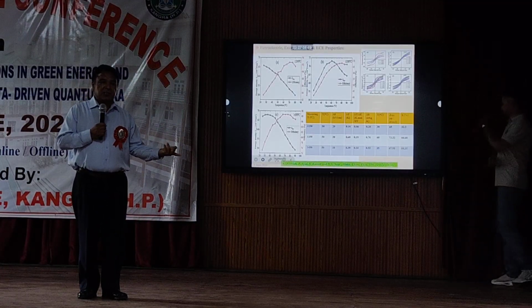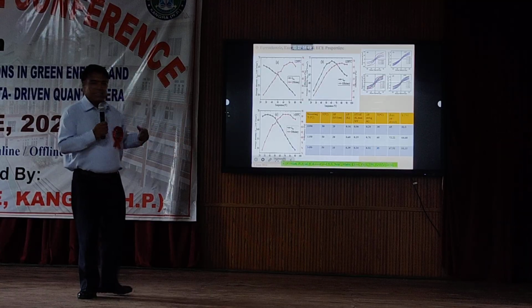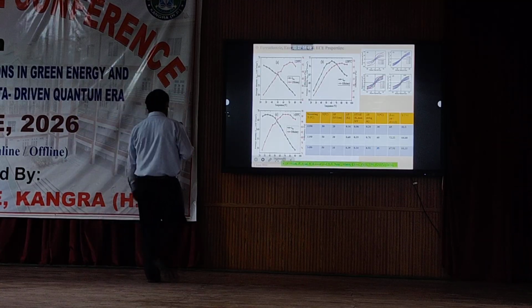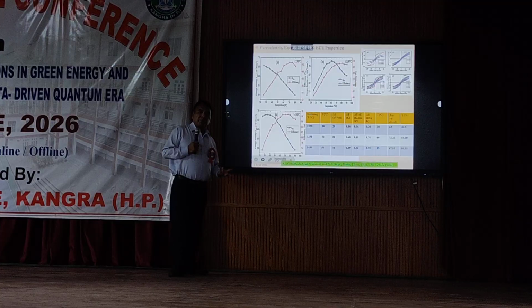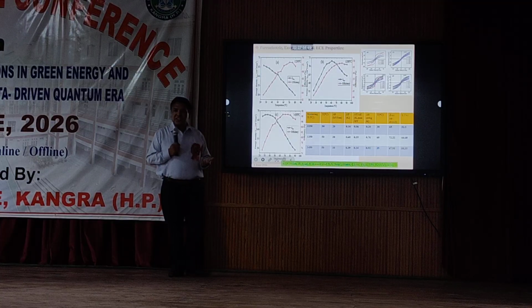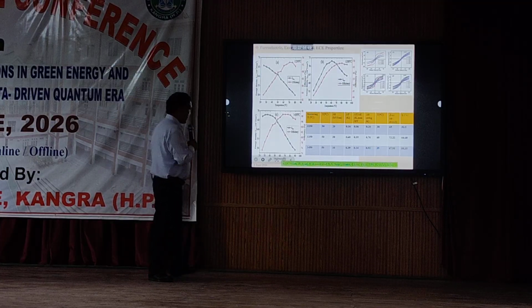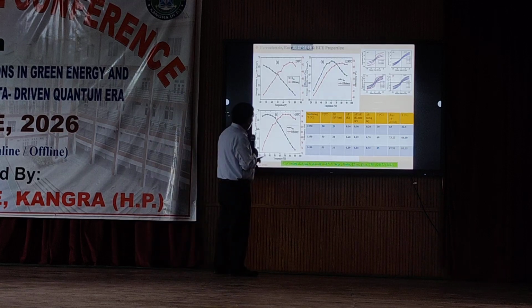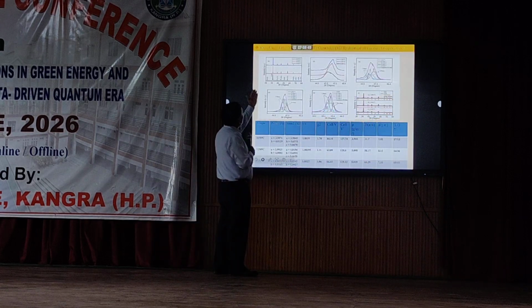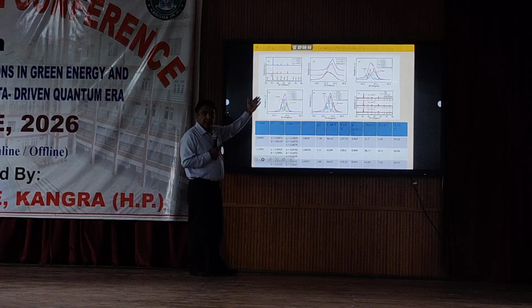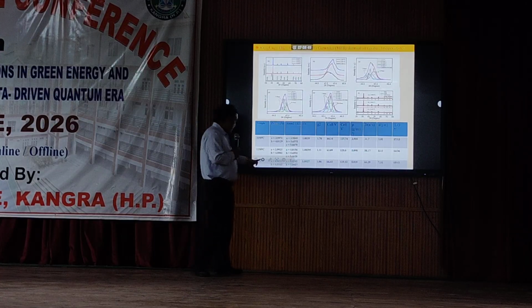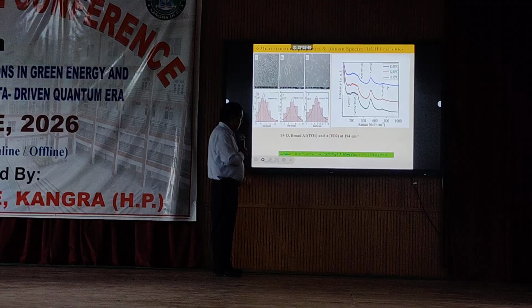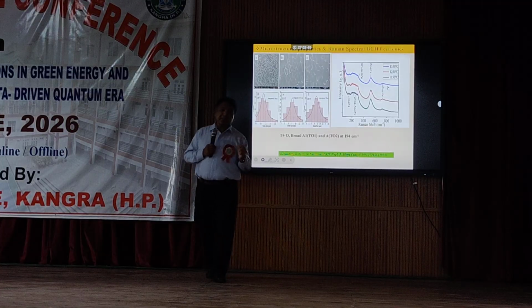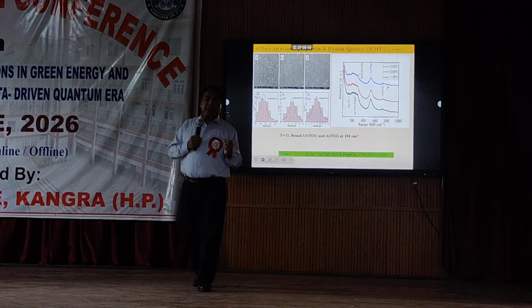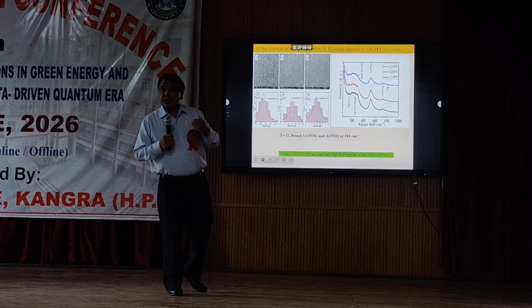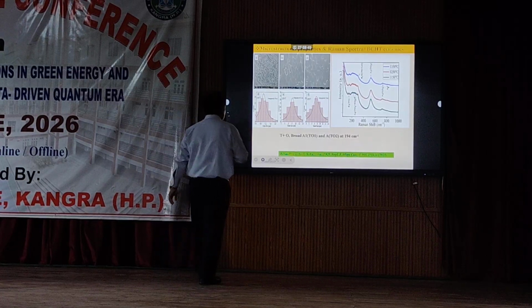Energy density increases, then efficiency decreases. So there is, I think, still an unresolved problem in this ferroelectric research, particularly for energy storage purposes. And if you see more results here, next we took that morphotropic phase boundary. Again, almost similar results we observe here, with a little enhancement in the delta T, that is the adiabatic temperature change, and a slight improvement in the energy storage density.